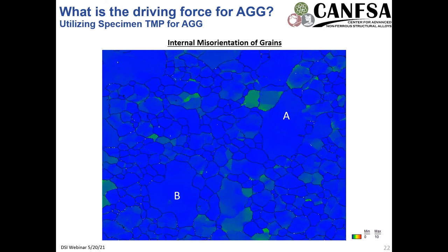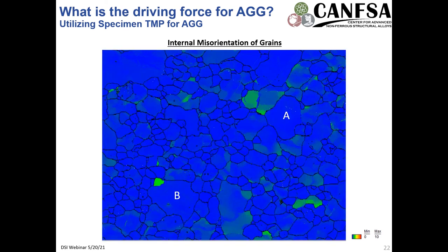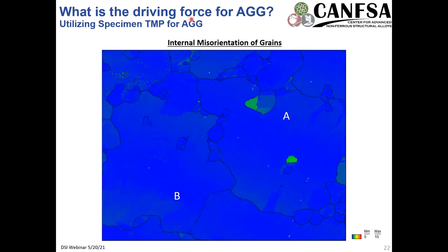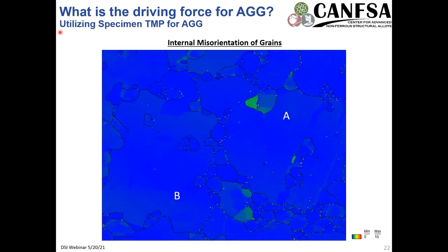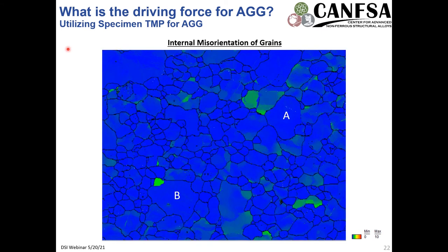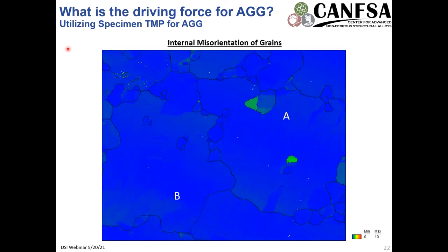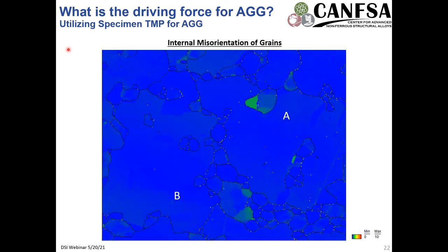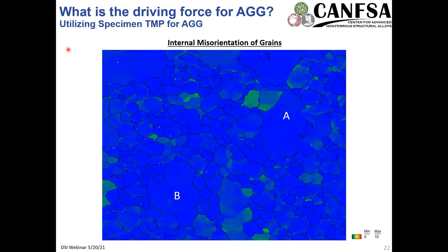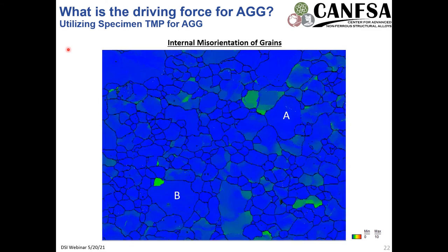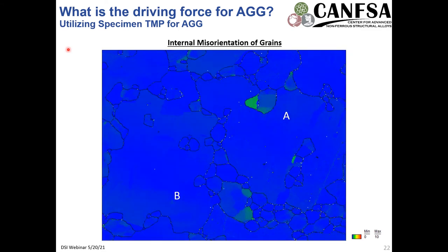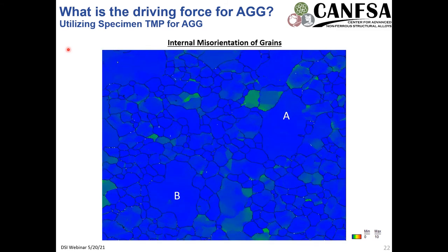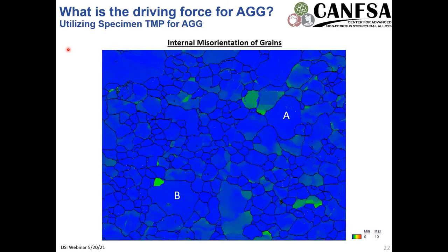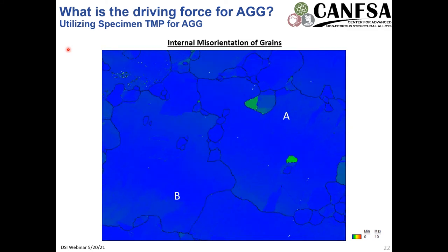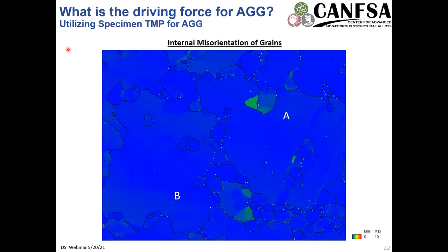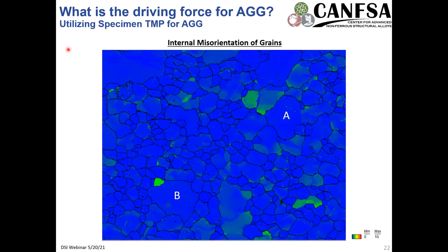And so here is an animated GIF of the material. This is looking at the driving force for abnormal grain growth, and this was processed in the conditions for thermomechanical processing that would create abnormal grain growth. I did interrupted heat treatments within a quenched dilatometer that was backfilled with UHP argon and then pulled down to 10 to the negative 6 torr vacuum. After that, it was slightly polished with 0.02 micron colloidal silica by hand, to remove a minimal amount of oxide on the material that formed during heat treatments.